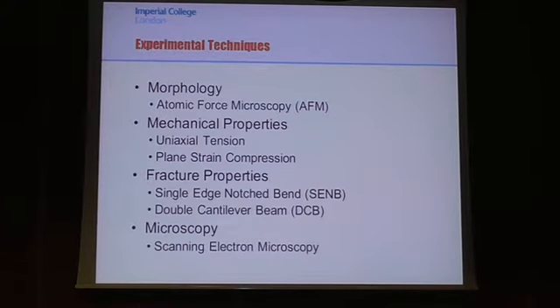So, we'll take a look at AFM now and the mechanical properties. We'll quickly go through tension and compression properties. Focus most of my talk on the fracture properties, so single edge notch bend tests for the bulk polymers and double cantilever beams for the carbon fibre reinforced polymers. And then, of course, when you do a fracture test, one of the most important things to do is you have to look at the fracture surface, because the answer to all of your confusing results is always on the fracture surface. We just need to learn to understand the language of the fracture surface.